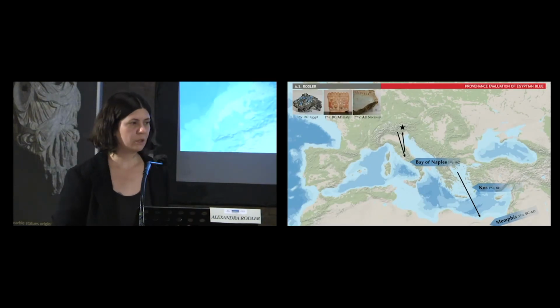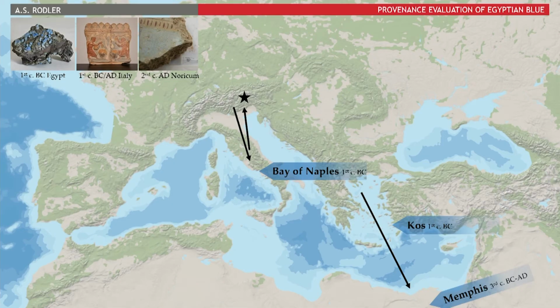So to put this in context, for the 1st century BC to AD, this fits with the small subset of samples from Noricum. We have results for Egyptian blue from Memphis that was made with Aegean copper, and then the Egyptian blue used for the Campania relief that I showed you earlier that was made from East Alpine copper, very likely, and at least in the last Egyptian blue from Noricum, the wall paintings and also the pellets from Noricum were made from Central European copper, so from the Eastern Alps again, or from Slovenia or Switzerland.